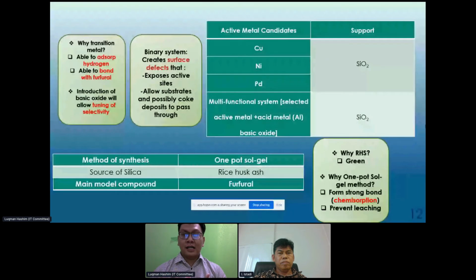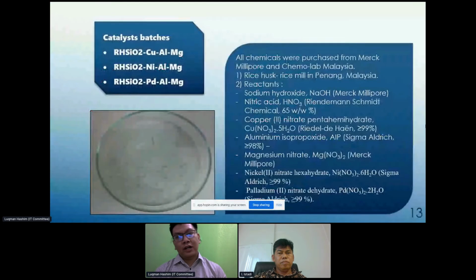Now we are going to do all of this synthesis using our one-pot sol gel method, mainly to create strong bonds between each element of our catalyst via chemisorption, therefore hopefully preventing the leaching process. Now on your left there, the catalyst batches are, as I stated, copper, nickel, palladium matched with aluminum and magnesium. On the right there are the materials I use. You may take a look at it.